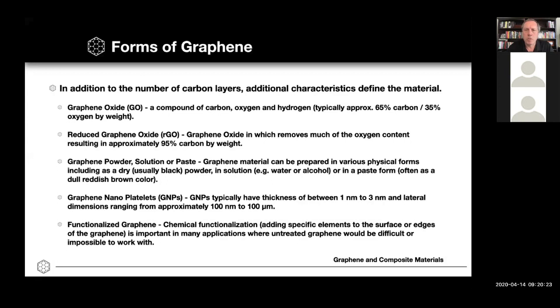In addition to this, we have materials such as graphene oxide, where approximately 35% of the material by weight is oxygen. You have a reduced graphene oxide. Graphene can be produced and delivered in the form of a dry powder. It could be in a solution or a solvent. It can be delivered as a paste. You have graphene nanoplatelets, which exceed the ISO definition of what graphene is, but they certainly have value in applications. And then you have an additional characteristic or iteration here where you have functionalized material. So there's actually material that's decorated on the surface or on the edges of the graphene flakes, for example, with other molecules or elements to give them additional properties to make them adhere better or to make them disperse more easily or whatever the objective might be.